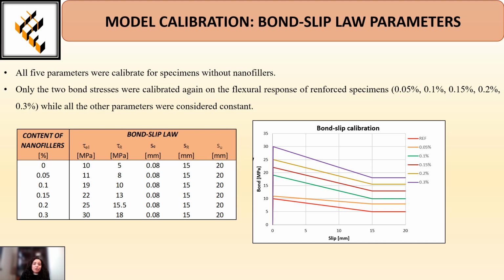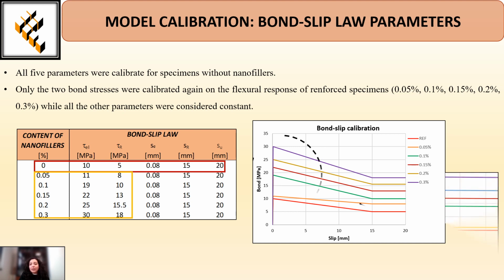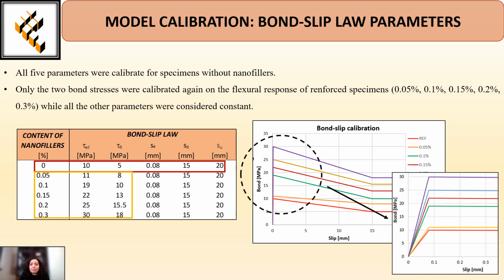For the calibration of the bond-slip law parameters, first of all 5 parameters were calibrated for the specimen without nanofiller, and then the 2 bond stresses were calibrated again for the reinforced specimens, while all the other parameters were considered constant. Here it's possible to see better the initial branches.